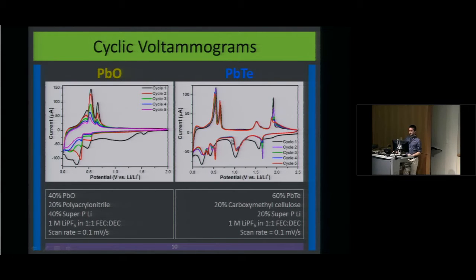For the lead telluride, you can see those humps stay there the entire time in subsequent cycles, so you're able to extract that lithium back out of your tellurium. You can also notice that with the lead oxide, the peak height decreases as you cycle, whereas it stays pretty much constant for the lead telluride. This has to do with the reversibility of the reaction. With the lead oxide, you're losing capacity for each cycle, which you don't want your battery to do. The lead telluride seems to perform much more stably.